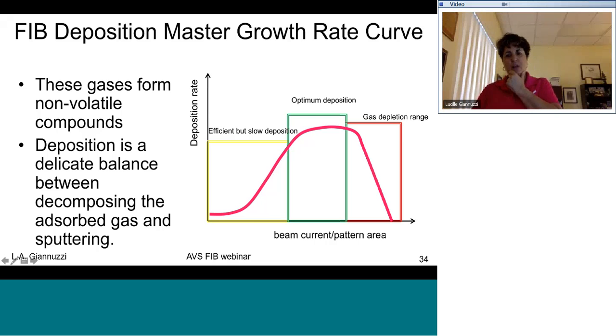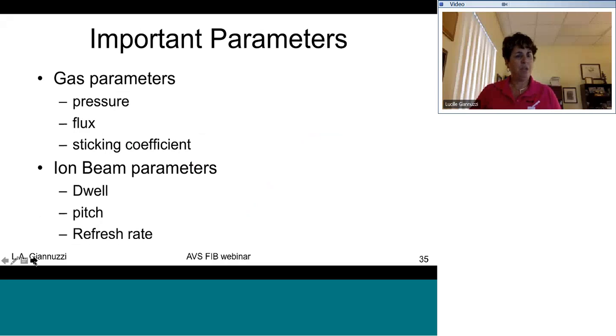And in the gas depletion range, what happens is that, as the name implies, there's not enough gas there for deposition to occur. So this occurs one of two ways. One is, if you've ever operated an instrument and you're not getting deposition, you're getting milling, it's because you can be just out of gas. The two, you can be using a beam current that's way too high for the pattern that you've defined. And so any vendor will generally give you a formula to use. That formula might be, for example, 2 to 6 picoamps per micron squared for the case of platinum or carbon in some materials. So the important parameters for gas deposition are the pressure, flux, and sticking coefficient.